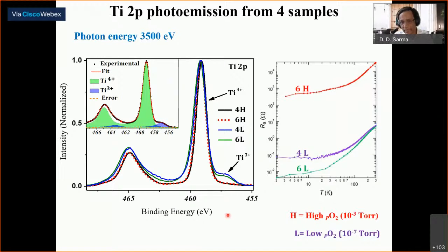But then what makes it metallic? It turns out that when you look at the core level of titanium, this huge big peak that you see over here is coming from titanium 4+, which is a strontium titanate signal as you would expect. This is the 2p3/2, and this is the 2p1/2. Let's not worry about that. It's just a spin orbit replica of this one.